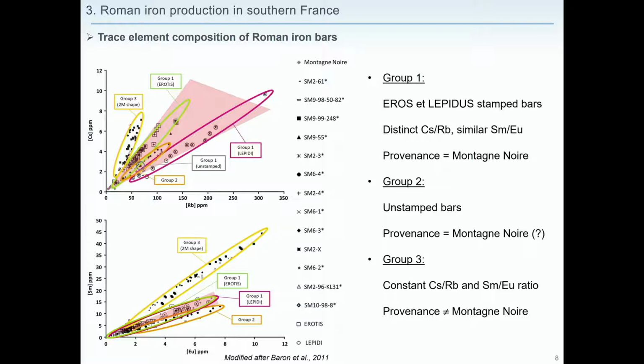Then we have a second group here with samarium to europium ratio, which slightly differs from the materials from the Montagne Noire. So here, the provenance from this region cannot be fully validated. And then we have a third group here with very constant trace element ratio for these two couples, and clearly out of the composition range of materials from the Montagne Noire, so the authors conclude to another provenance for these bars.